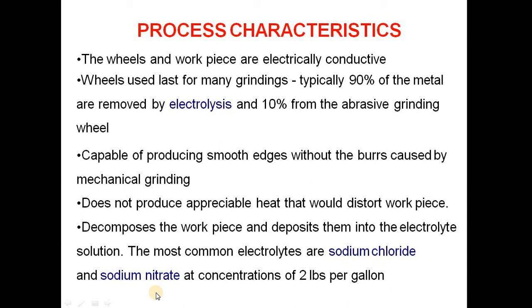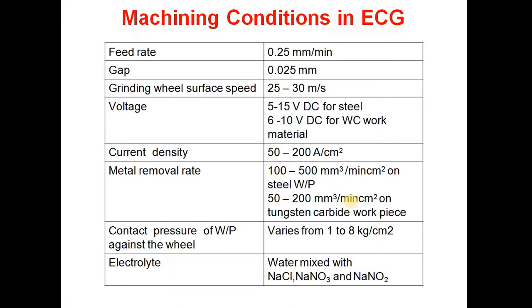These are the two electrolyte solutions which can be used to remove the material at a concentration of 2 lbs per gallon. So what are the machining conditions for ECG? There are different machining conditions for ECG which are commonly used. That is feed rate up to 0.25 mm per minute, gap is 0.025 mm, grinding wheel speed is near about 25 to 30 meters per second, voltage 5 to 15 DC volts applied, current density is 50 to 200 amperes.